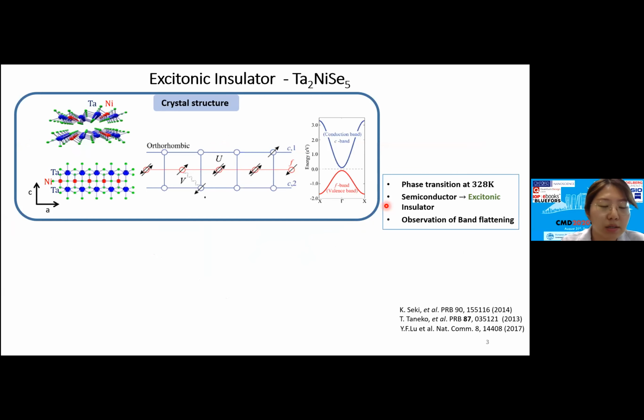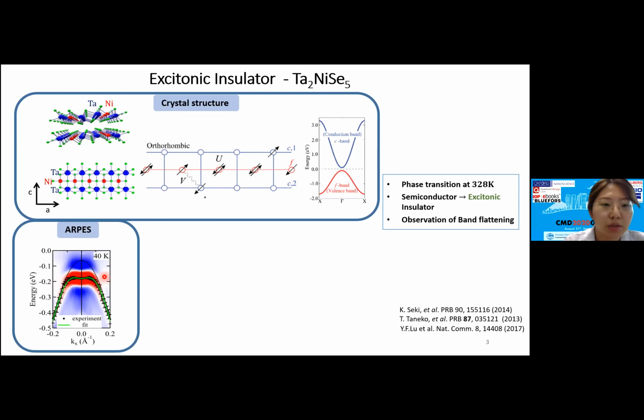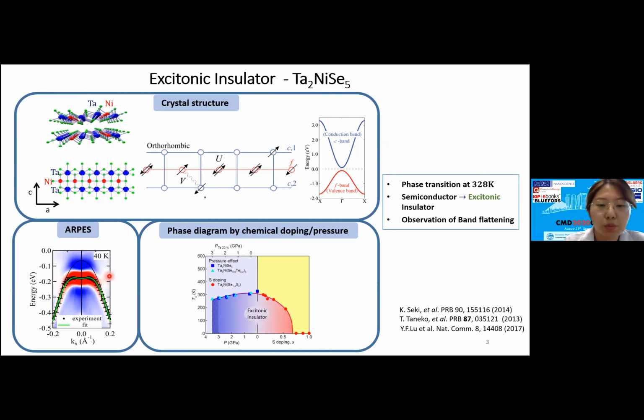This sample crystallizes in a quasi-one-dimensional chain structure, and electrons hop from nickel to tantalum and form a charge transfer exciton. The system has a direct band gap, which means we can avoid charge density wave contribution when we study this insulating transition. Experimentally, we can see the characteristic band flattening because of the condensation, as you can see in ARPES measurements. Transport measurements also show that Tc is changed by doping. So you can see this characteristic phase diagram of an exciton insulator, but we are still missing the coherent dynamics of the collective mode of the exciton insulating state.